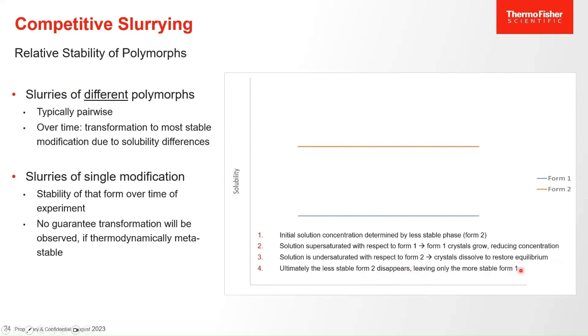This is the only reliable experimental method for determining relative stability of polymorphs. Slurries of a single modification only tell you the stability of that modification over the time of the experiment, as there is no guarantee that a transformation will be observed if your phase is thermodynamically metastable.